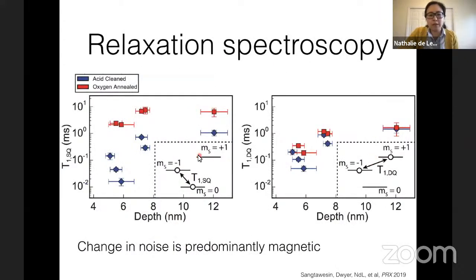We can also take advantage of the fact that the NV center has a spin 1 ground state and do relaxation spectroscopy to try to disentangle whether we're mostly looking at magnetic or electric field noise. So the general idea is that magnetic noise can drive these single quantum transitions that change your angular momentum by 1, but it generally will not drive transitions between your ms equals plus and minus 1 sublevels, whereas electric field noise can actually couple these things.